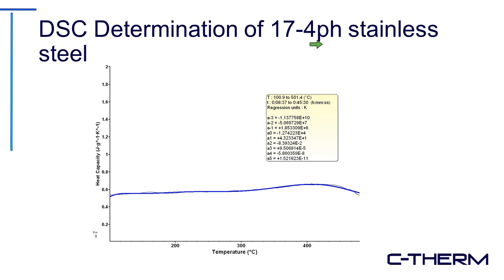So this is exactly what I did in this run. We looked at stainless steel AM powder, and specifically from 0 to around 500 degrees Celsius. You can see that the heat capacity does change with respect to temperature, which is important to know over time. So by measuring this, we're able to show that specifically at different temperatures, the heat capacity of that powder with respect to the process that you're trying to generate. So if this is in a stream, you want to know specifically the stream is running at 200 degrees Celsius, we're able to calculate that heat capacity, which is very important when you're doing modeling of these processes in general.